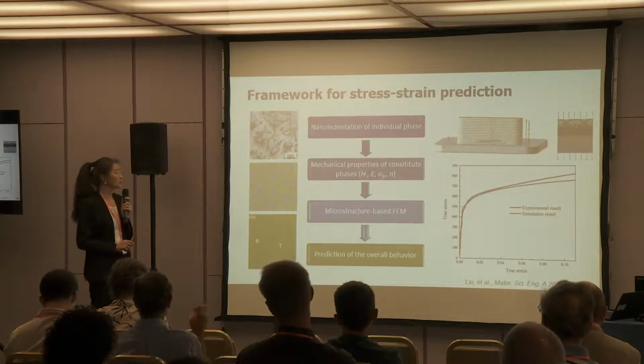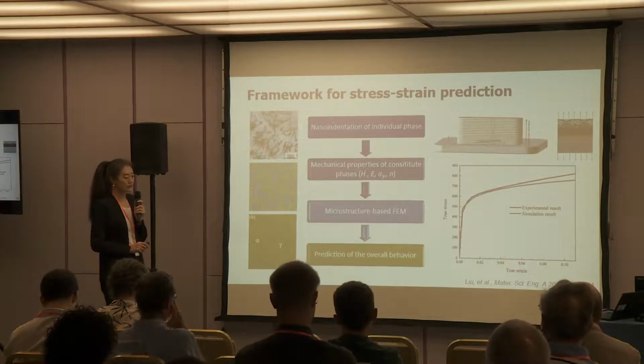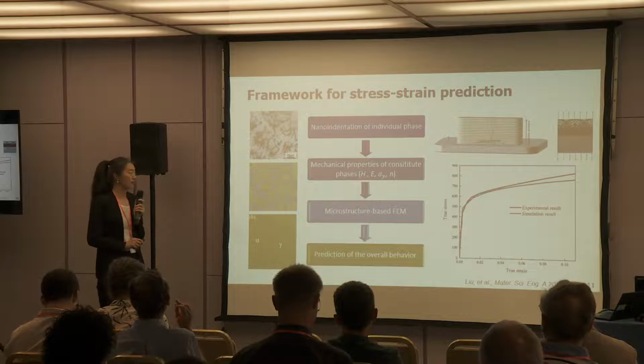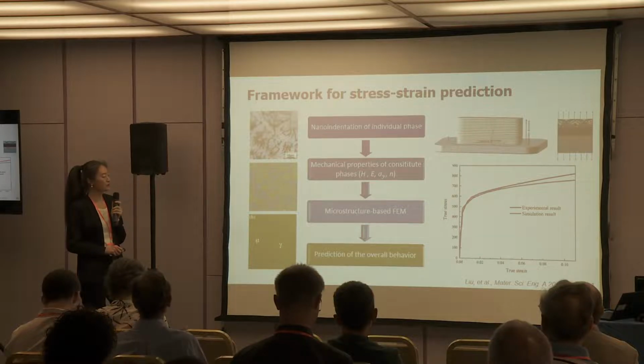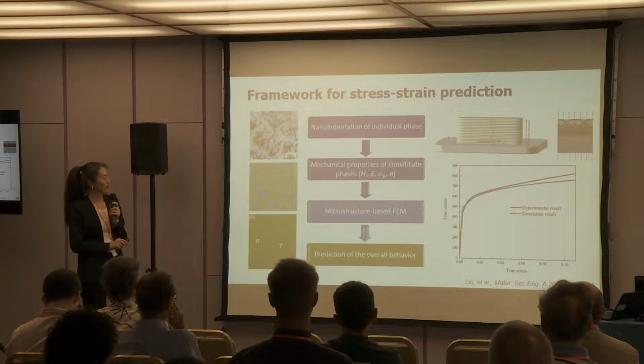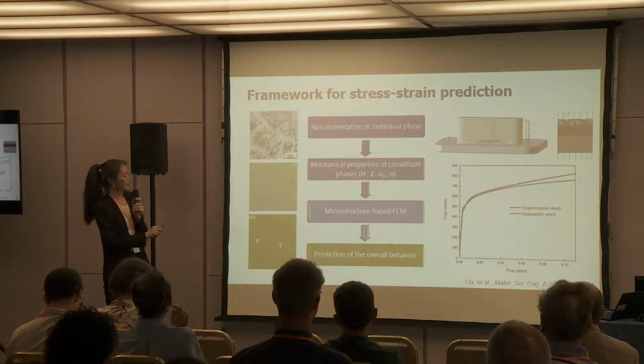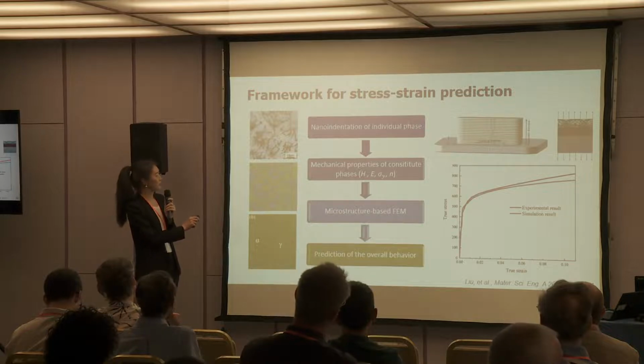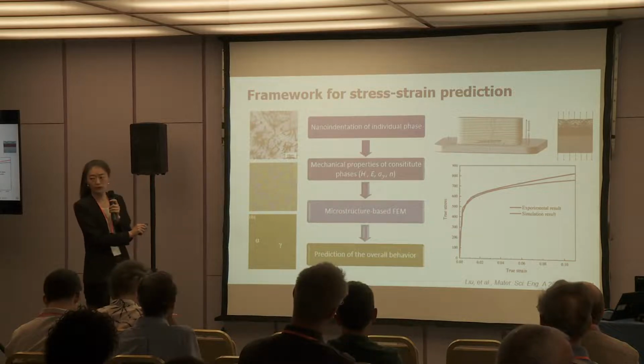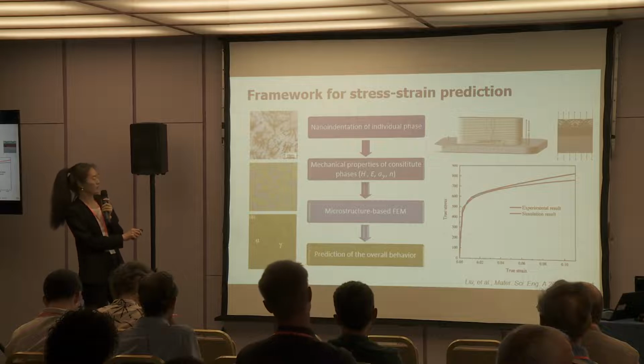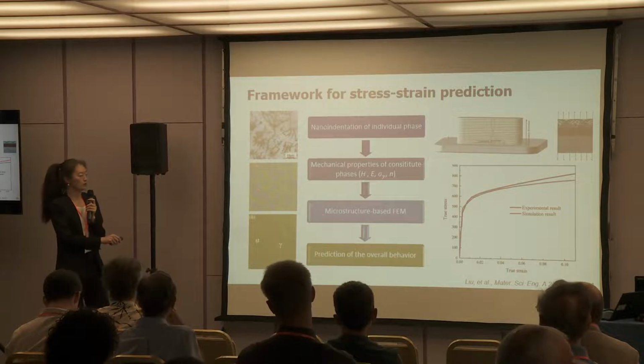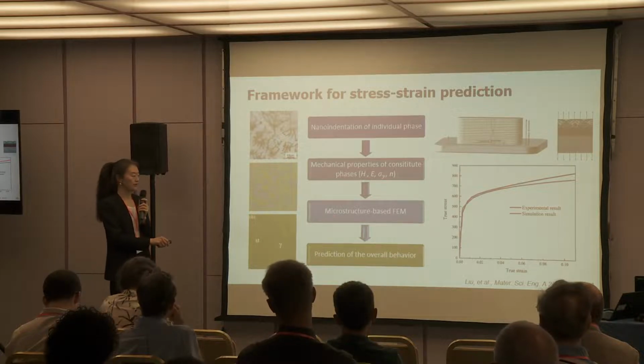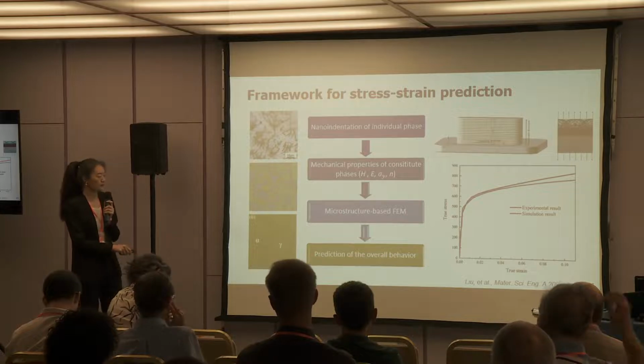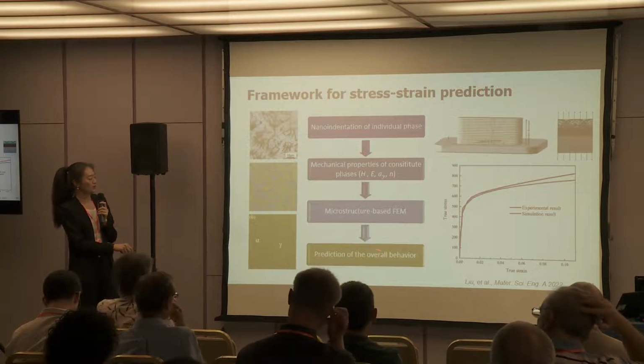We also developed a framework for local stress-strain prediction by combining nanoindentation and microstructure-based finite element modeling. And here, as long as we have the microstructure of the material, using nanoindentation we are able to obtain the mechanical property of each individual constituent phase. And we use that as an input parameter to the microstructure-based finite element model. Then we are able to predict the overall behavior of the structure.